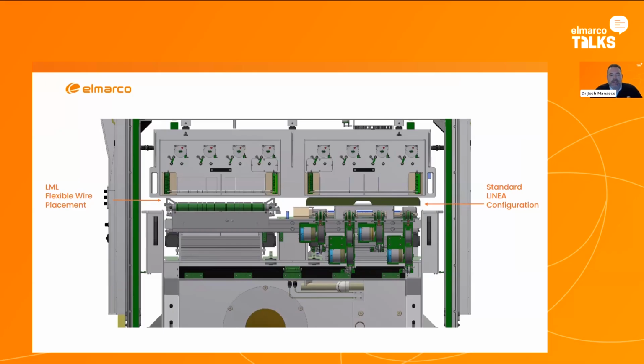So we came up with a system where you can have a flexible wire spacing. This is that, on the left side you can see there's a cylinder with different notches on it. That's where you can place different numbers of wires. So we designed this so that we can have a testing machine on the industrial scale to prove this out. And then on the right side is just the standard machine where you have four wires. One machine would typically have eight wires total. It has four on the right, which is a standard setup, and on the left is a customizable setup where we can change the spacing to try different spacings at the industrial scale.